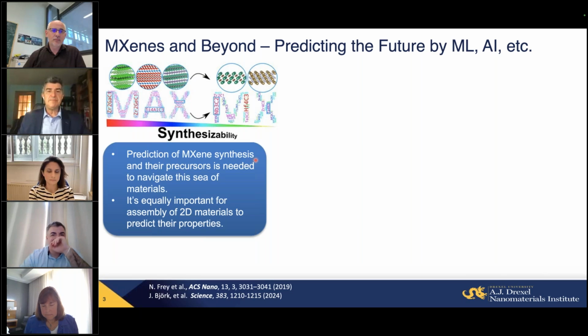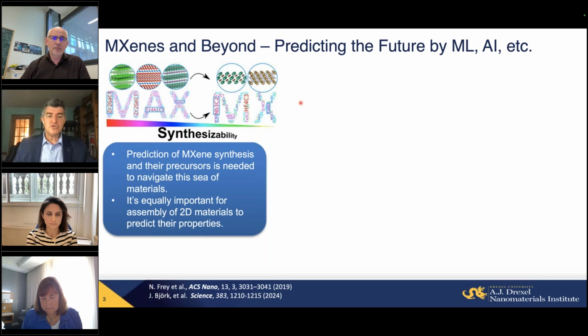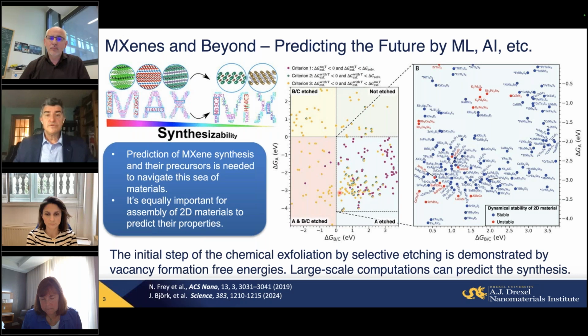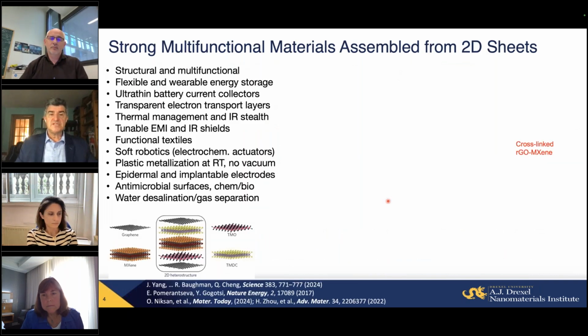Naturally, you cannot experimentally make an infinite number of 2D materials here. We also use DFT prediction and machine learning. This is from some earlier work with Vivek Shenoy. Other groups also do similar prediction, how, for example, to make MXenes out of MAX phases, so known MXenes, by removing an element. And this is work from Linköping recently, predicting not only carbides, but also two-dimensional silicides, synthesizing one of them to confirm here. So clearly, computational science, machine learning, artificial intelligence will lead us to the world where we have all the necessary building blocks to create this type of multifunctional materials by combining different structures.